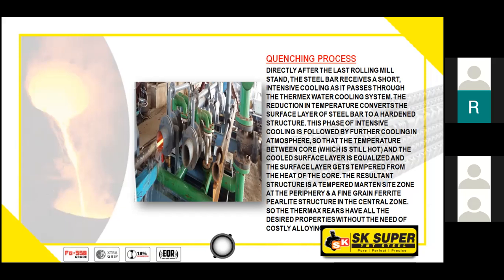Now, what happens when these bars go inside that pipe, which is full of water? The temperature of the bar while going inside is about 900 to 950 degrees centigrade. Within a fraction of a second, I'm talking within a fraction of a second. Being in this industry for the last 18-19 years and working with big institutions, you can see the bar going inside from one side. You can't see the bar coming out from the quenching process at the same time.